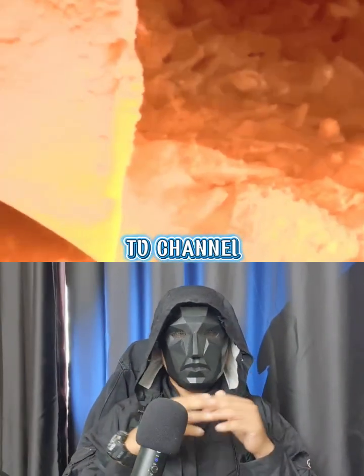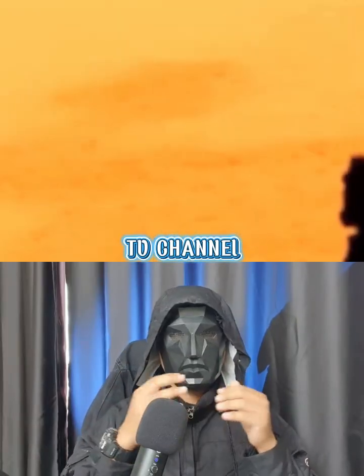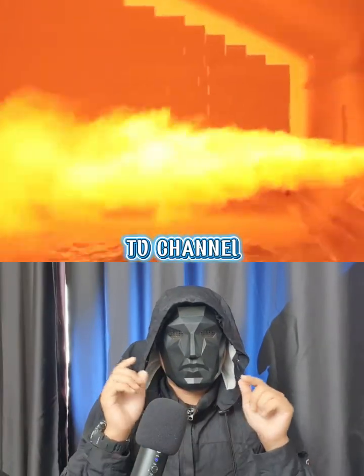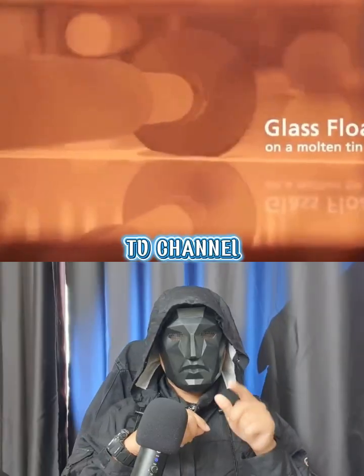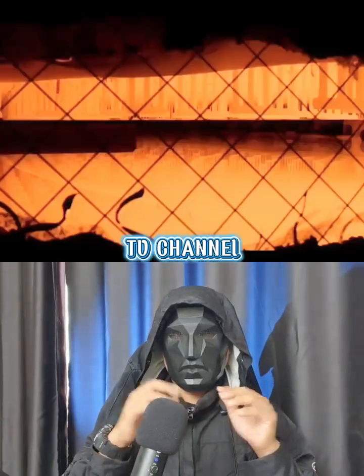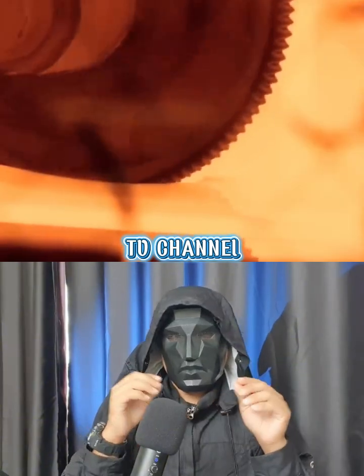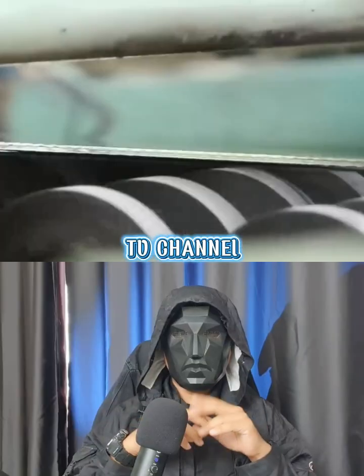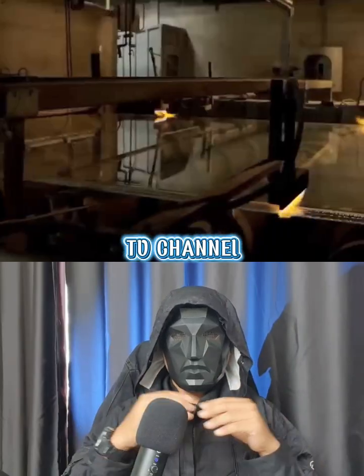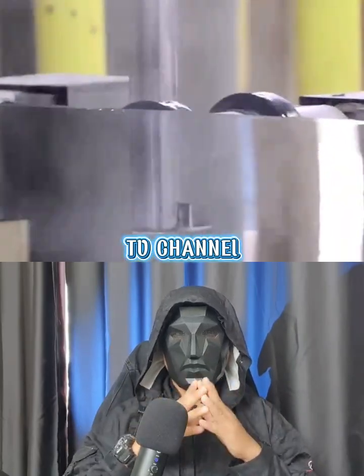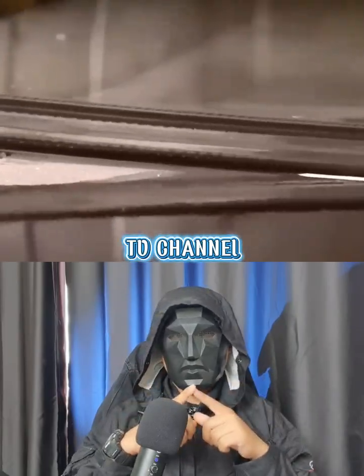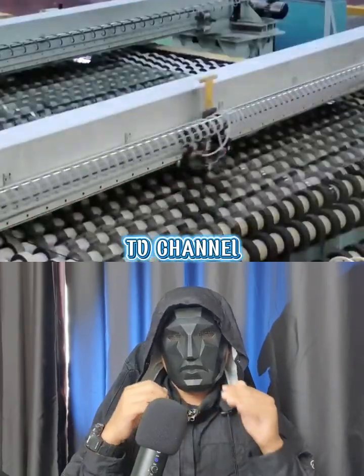The raw material batch is fed into a large furnace and heated to extremely high temperatures, typically between 1500 degrees Celsius to 1600 degrees Celsius, or 2700 degrees Fahrenheit to 2900 degrees Fahrenheit. The silica sand melts and transforms into a molten viscous liquid. Refining and homogenization occur in the furnace to remove gas bubbles and ensure a uniform chemical composition.